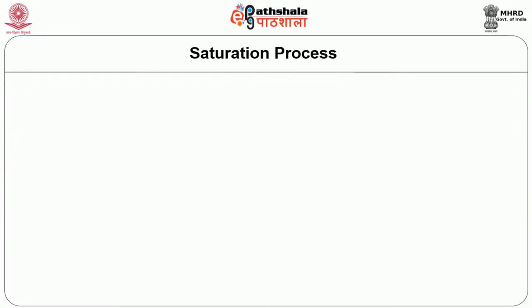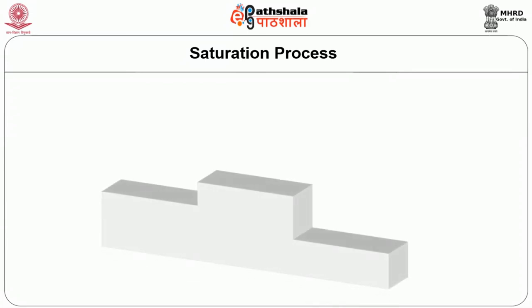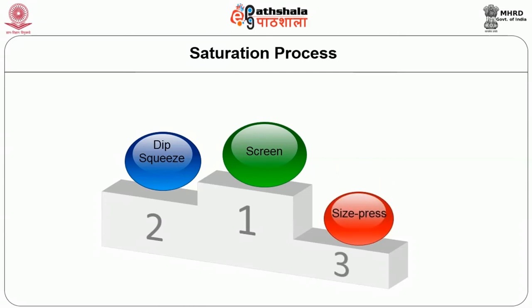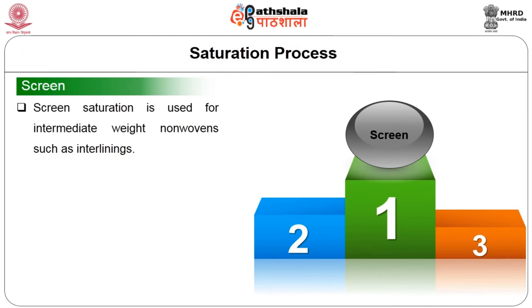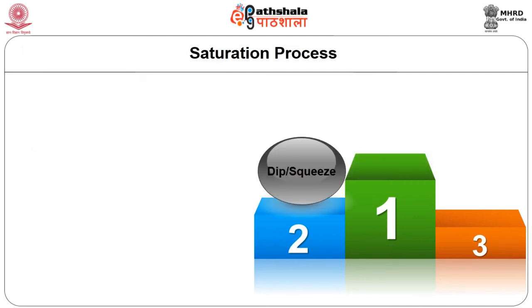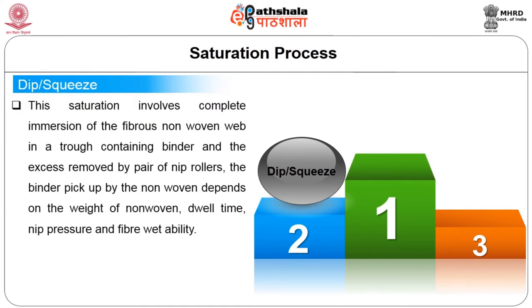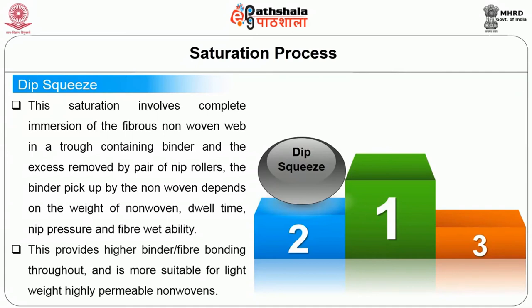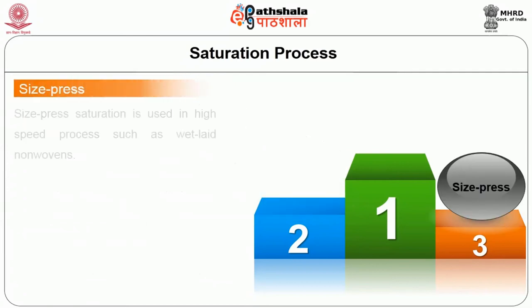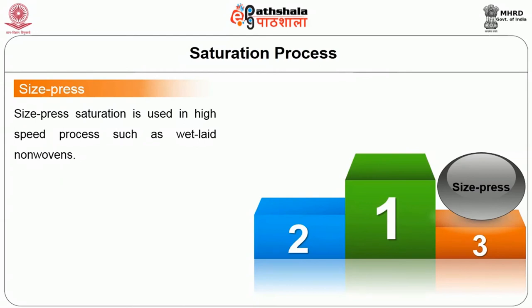Now, saturation process. Saturation bonding can be carried out in three ways: using screen, dip squeeze, and size press. Screen saturation is used for intermediate weight nonwovens such as interlinings. Dip squeeze saturation involves complete immersion of the fibrous nonwoven web in a trough containing binder and the excess removal by a pair of nip rollers. The binder pickup by the nonwoven depends on the weight of the nonwoven, the dwell time, the nip pressure, and fiber wettability. This method provides higher binder to fiber bonding throughout and is more suitable for lightweight, highly permeable nonwovens. Size press saturation is used in high speed processes such as wet laid nonwovens.